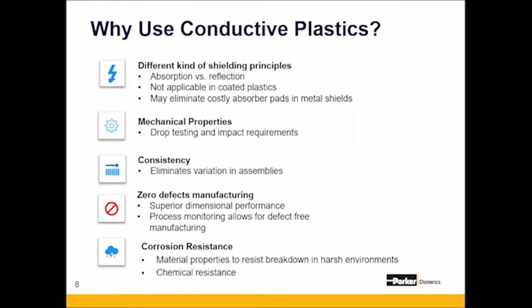There's also a lot of dimensional benefits to conductive plastics. The goal is always to get closer to a shoot and ship part. You want to get to 0 defect manufacturing. You can do that through process monitoring, where you establish the molding parameters. You can get very consistent part-to-part results. You can also minimize variation from shot to shot, dialing in those process parameters. When you think of a machined tolerance on a diameter of, say, 12 millimeters or a 1/2 inch hole, you can actually get plastic parts to vary by less than 10 microns on small parts like that. And this isn't utopia. This is just good upfront planning.